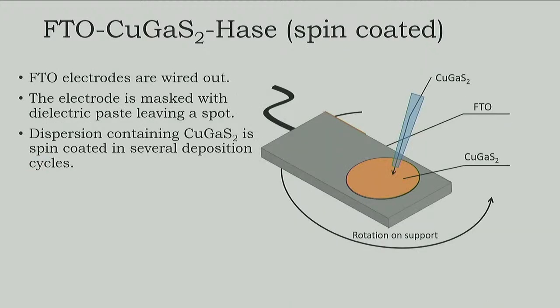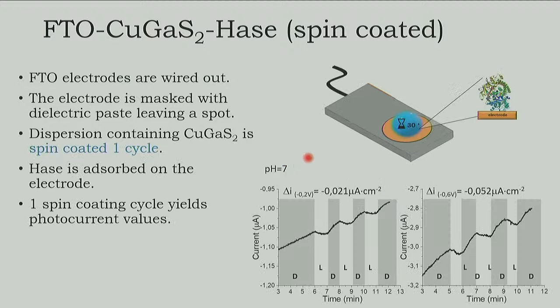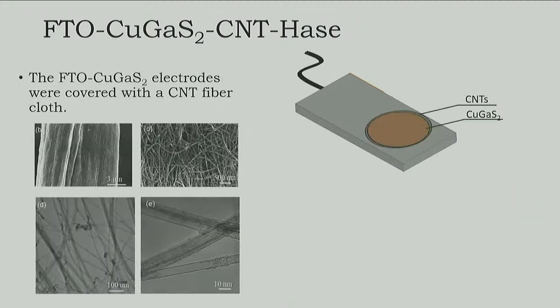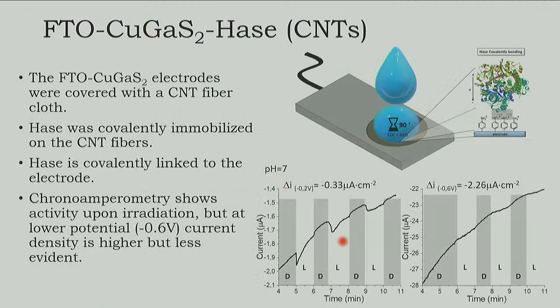So what if we do a spin coating? More or less we're getting the same kind of response, a little bit higher, but still not good enough for us. And later we tried to put carbon nanotubes on the surface of this. We modified it to see if immobilizing the enzyme on the carbon nanotubes gives a better response, and we have to illuminate. These electrodes are transparent. We only cover them through this side. We immobilize this way here, and we get this kind of response. Also, in some cases, it's not very good.